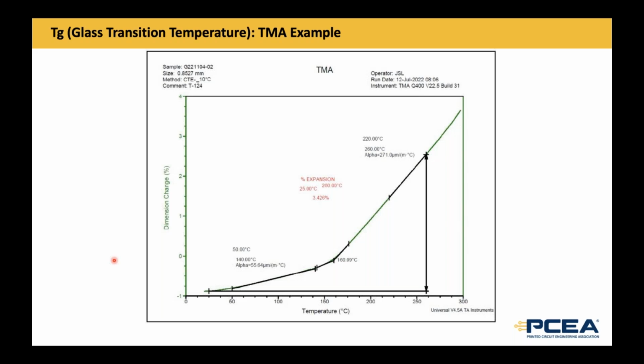So this is a typical scan of what would be an FR4 material, a very common material. This was done in a test in a consortium that we're a member of, as a function of about 500 different tests to evaluate and quantify the ability of TMA to measure TG accurately. What you see in this scan is that the curve has a deflection point, and you can see right there it's around 160 C. It's hard, because of the way the tangent lines have been drawn across it, to see the whole line, but basically the rate of expansion below that TG and the rate of expansion above that TG